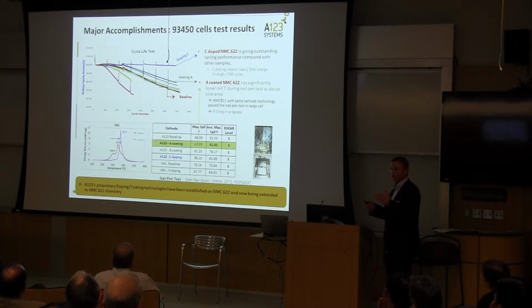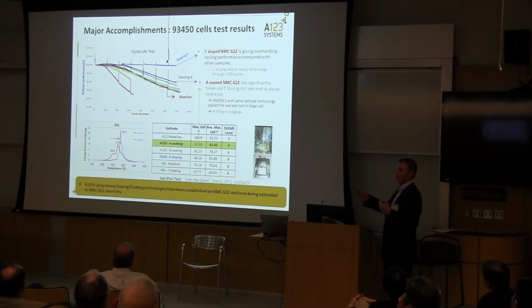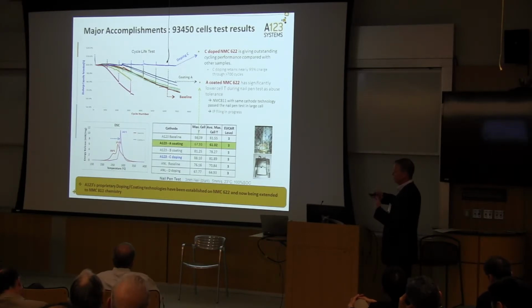But then what we've done is we've taken that and built full-size cells between 50 and 60 amp hours to say, okay, if we get this response from the APS or this response from DSC, what does that translate to at the cell level? Well, if we make some changes, like let's say to a 70% nickel, we get this same sort of response that we would get from something that would be 50% with no coating. We get the same DSC, the same APS sort of response. Do we get better abuse performance? And so this is really what this is highlighting.